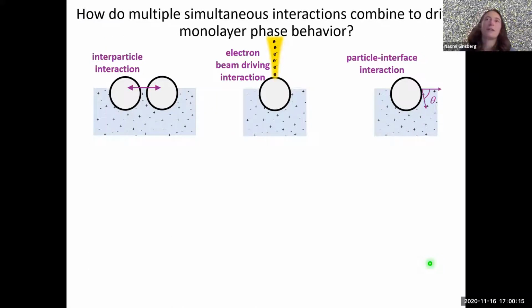And I'll just tell you up front, there are 3 interactions that we're going to need to focus on. So interparticle interactions, the interaction between the electron beam that's driving the dynamics and the particles, and then also the interaction of a particle with the interface. And that makes it sound really simple. It actually took a lot of effort to isolate them this clearly and also to determine how they balance with respect to one another.